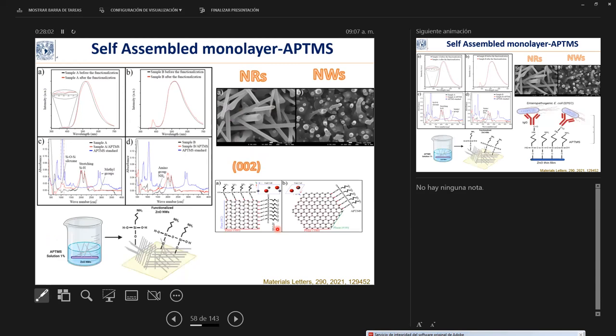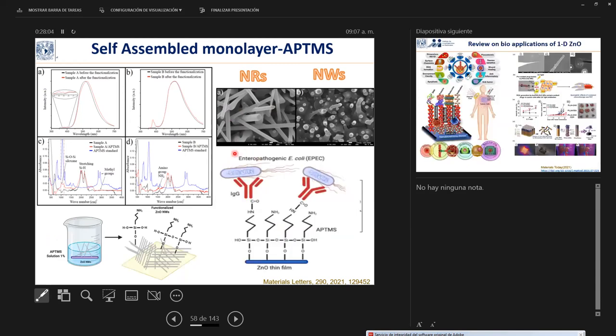So of course, there are some changes between the nanowires and nanorods. And we found that whenever we want to increase the interaction level, we want to increase the sensitivity of the device. So it's always preferable to grow the material in this particular orientation that will increase the polar surfaces, and we can have more sensitivity from the material. What is the final aim of this particular detection system? Now we know our nanowires and nanorods work as optical biosensors. We have done some studies on the physical interaction part and on the orientation of these nanowires. We know now how sensitive they can be and how we can increase the sensitivity of the whole system.